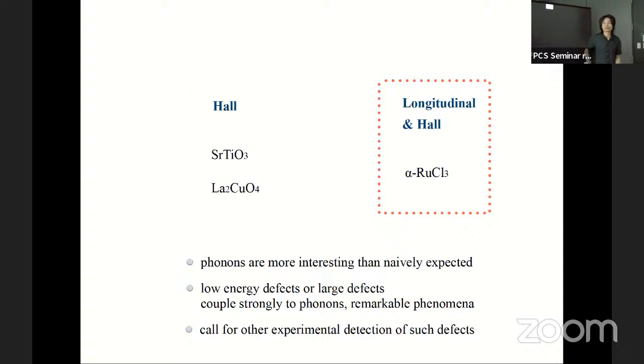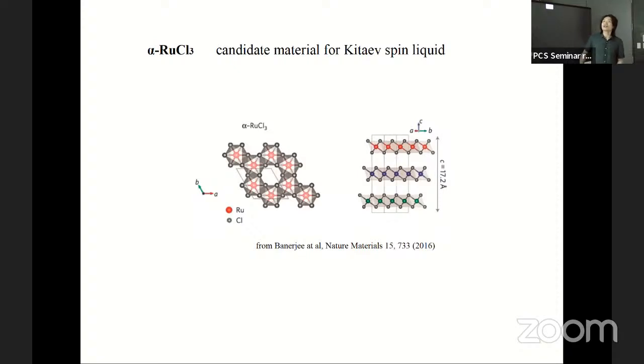Let's briefly talk about this for about five minutes or so. It's a candidate material for Kitaev spin liquid, and it's a quasi-2D material with different layers. In each layer there's some Kitaev term, but because there is also the Heisenberg term of the spins and so on, it's not necessarily a spin liquid. Most likely it is not. But at least it has a Kitaev term in the spin sector, which means the spins are not a usual simple ferromagnet or antiferromagnet. The spins have very strong frustration among themselves. So that's an important material property that we need to remember: the spin degrees of freedom are complicated and have strong frustration.